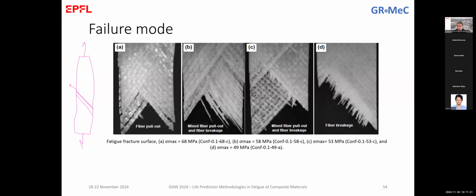When we are at lower stress levels, we have significant damage everywhere in the matrix, and this led the fibers in the location to be weaker because they were not supported anymore by the matrix, and that's why we could see this local fiber failure.